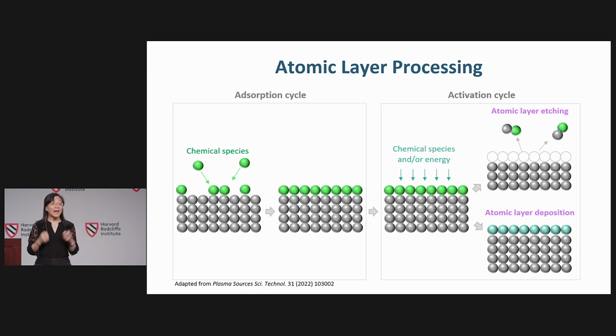Then we switch the process to an activation cycle. In this activation cycle, I bring in a second chemical species, or I use an energy transfer process, or both. Depending on what I do here, two things can happen. One, the absorbed layer on the surface can be converted into a solid and stay on the surface. This is an addition of a layer to the surface, and we call this atomic layer deposition. Or the layer that you introduce to the surface binds so strongly to the first layer of the material, weakens its interaction with the underlying layer, and you pour it off into the gas phase. You remove one layer of material. This is a subtraction process, and we call this atomic layer etching.